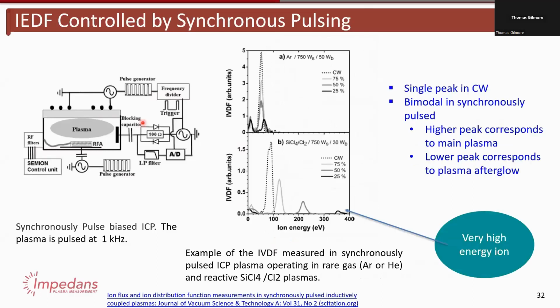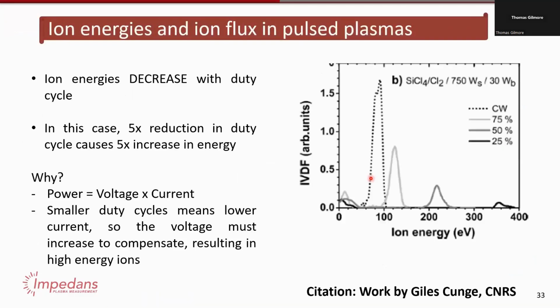Here's another example. How does that impact ion energies as well? What happens to ion energies as you're doing pulsing? As you change the duty cycle, you change the ion energy. The smaller the duty cycle, the larger the energy. So you can use this to achieve quite high energies if you wish. Again, you can think about this as delivering more instantaneous power. But actually, let me give you a kind of overview here.